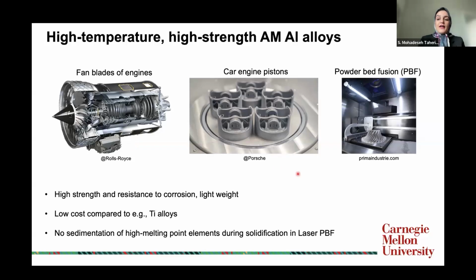So we thought when additive manufacturing like laser powder bed fusion came, maybe this class of alloy can emerge because you do not melt everything together and you just melt layer by layer. And aluminum is a choice because it has a higher strength, is resistant to corrosion, lightweight even compared to titanium, and much lower cost, 3 to 10 times lower than titanium, for example, for these fan blades. And titanium is a bit overqualified for this application.